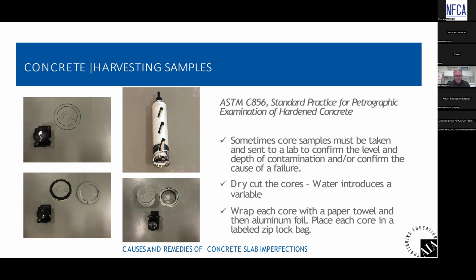And actually, if we're worried about crystalline silica, there are attachments that go on the diamond hole saws, a vac attachment that you can hook up to a HEPA vac system so that we can operate without creating dust. But we want to dry cut so that ultimately we can harvest that core sample that has a complete assembly, the complete flooring assembly intact for the lab to peel back layer by layer like you're peeling back an onion.